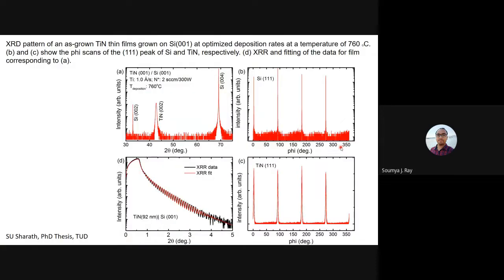Okay, so now I have taken a figure from a thesis. It shows how these two techniques in combination can work and give us very useful insight. For example, in this case, this is a titanium nitride thin film which has been grown on a silicon 001 substrate. This is the Z oriented substrate, and this is the deposition condition: 760 degrees Celsius was the substrate temperature.